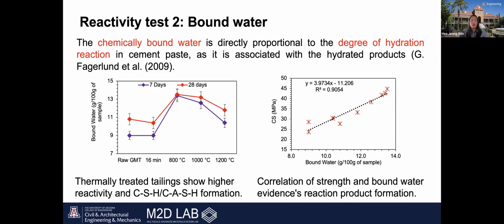And now that we have achieved a higher strength, we wanted to know whether the tailings actually reacted or just acted as a filler. One way to check this is by measuring the chemically bound water, which shows the degree of hydration. The chemically bound water becomes part of the crystal or gel network of the hydration products, like CH and CSH. And when the sample is heated, the OH groups in these structures are released, causing weight loss.